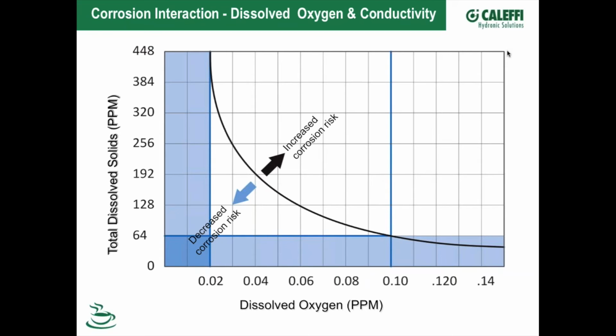Hey, Bob, this is Jody speaking. The other one to consider on this is control leakage. For every gallon of water that exits, a gallon of water has to come back in, and there's a good chance that water coming in is going to be oxygen and air saturated. Depending on how tight your system is, this can be a very significant factor in the continuing injection of oxygen into the system, faster than it can be consumed, on a big commercial job where there are a lot of leaking seals or air vents. That's a good point.